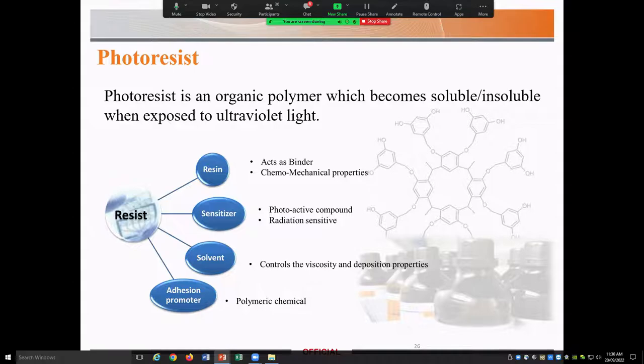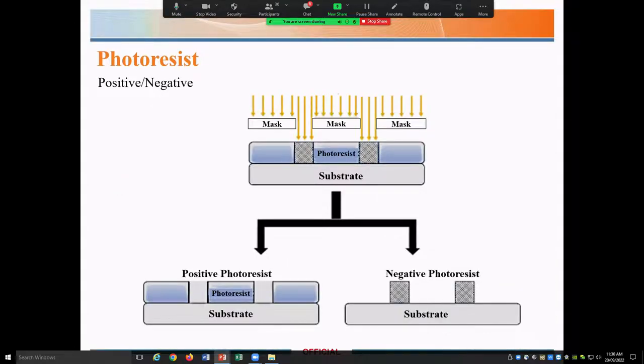Depending on how photoresists respond to radiation, there are two main types of photoresists, positive and negative photoresists. Let's see how they behave when they are exposed to UV light. With positive photoresists, wherever the resist is exposed to UV light, it becomes soluble, and later in developing solution, it will be dissolved away. So from this, we can tell that we get the exact pattern from the mask onto the substrate. But with negative photoresist, it works the other way around. Wherever the photoresist is exposed to UV light, it becomes polymerized, and this cross-linked polymerized photoresist is less soluble. And then in the developing step, the exposed areas remain on the surface, and the rest will be dissolved away. So with negative photoresist, we end up having the reverse of the pattern from the photomask onto the substrate.